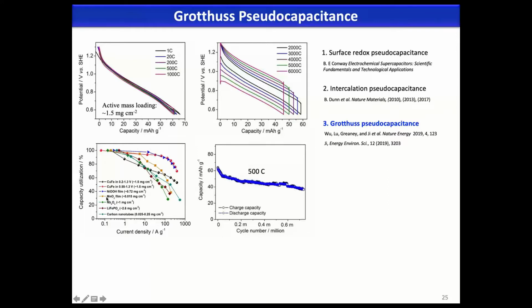We have only one comparable behavior, which is the nickel oxo hydroxide film, but that is really thin and pasted on some mesh, if I remember correctly. So this is really fast. As I just said, we don't have to diffuse ions through the structure. It's really different from the existing mechanisms nicely laid out by our peers, for example, the surface redox behavior and the intercalation pseudocapacitance by Professor Dunn at UCLA in a series of papers. We don't have to rely on diffusion at all. So we gave it a new name, Grotthuss pseudocapacitance.